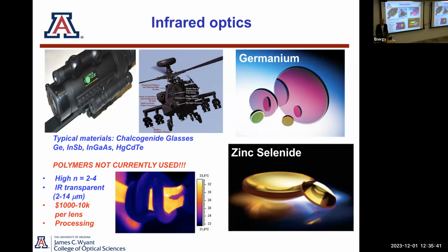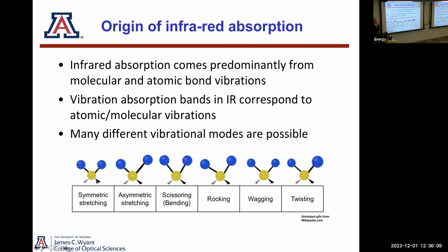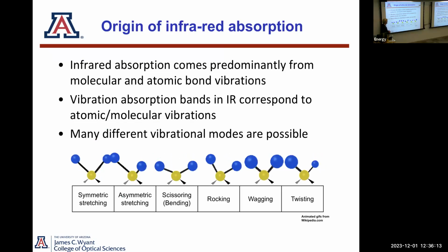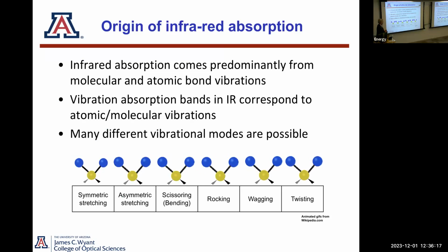But infrared optics has been occupied primarily by crystalline semiconductors that have heavy atoms like germanium, zinc selenide. Silicon itself is not bad. Chalcogenide glasses, which include things like arsenic and sulfur, but polymers not so much, for reasons we'll see shortly. So infrared absorption comes from nuclear motion. That's generally known. You can have very low bandgap semiconductors where it's still electronic absorption, but generally we're talking about oscillating nuclei and bond vibrations, and these correspond to various kinds of vibrational modes.